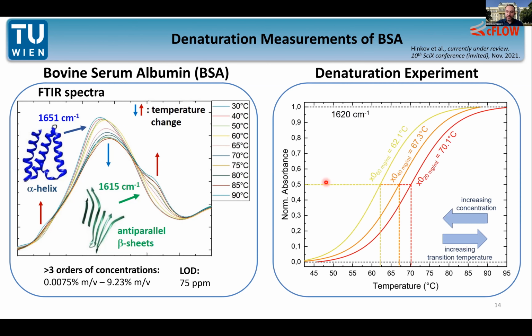And what we get actually are those results. So we look at the normalized absorbance curve as a function of temperature for different concentrations of BSA. And if you see here, if you go from 2, 4 to 6% of concentration, we basically see a continuous trend. So with increasing concentration from right to left, the transition temperature, where this transition from helical to sheet structure takes place, goes down. And this is very nice, because if you compare it to literature results on, let's say, lab scale setups, the ones I showed you before, that's exactly what they also observe. So we could really validate the proper operation of our on-chip sensor by comparing it to literature, but now we do it really on the fingertip.